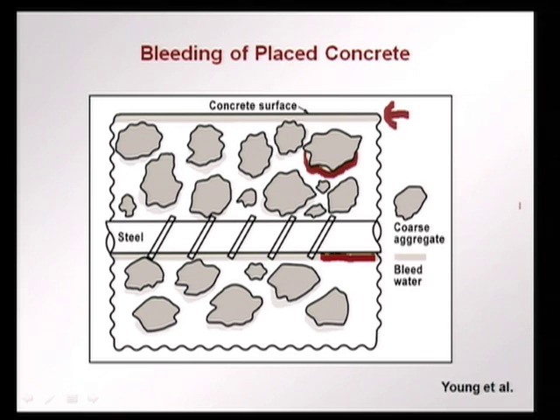The only positive thing about bleeding is that as bleed water rises to the top, if there is a lot of evaporation, then this bleed water is removed instead of water being pulled out of the concrete. So, if the curing is bad and you have a weather condition where you have a lot of evaporation occurring, bleed water helps because it protects the rest of the concrete. However, it is not an excuse for doing bad concrete and encouraging bleeding. Curing is the best option to avoid shrinkage, cracking and so on.